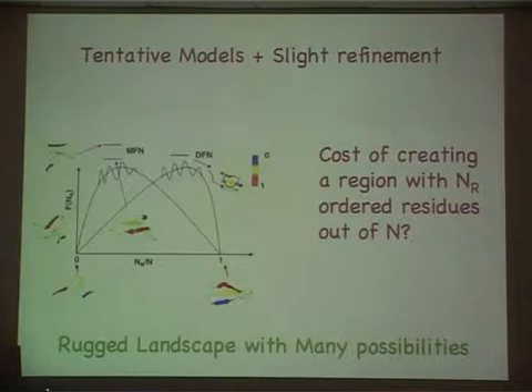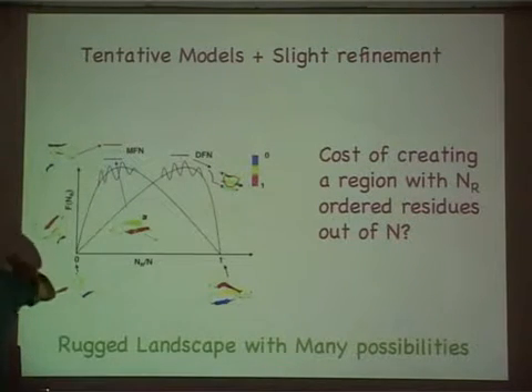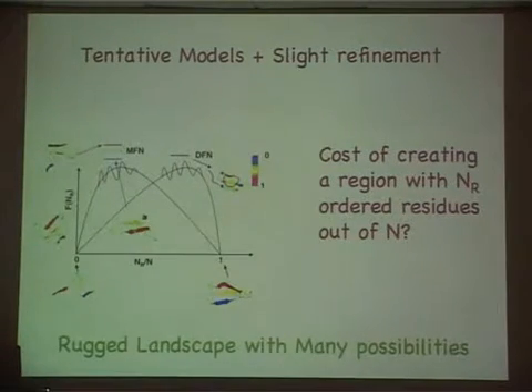Due to looping, is it just the fact that you have a heterogeneous surface? No, the fact is that it's a polymer chain, and then if I bring some piece together, I'll necessarily form some loop, and that's a loss in entropy because it forms a loop, and I've got to worry about that. That usually in a polymer for large N goes as the logarithm of N, and you don't worry about it, and I won't worry about it here. But although you should think about it, for short chains, it can make quite a bit of difference.